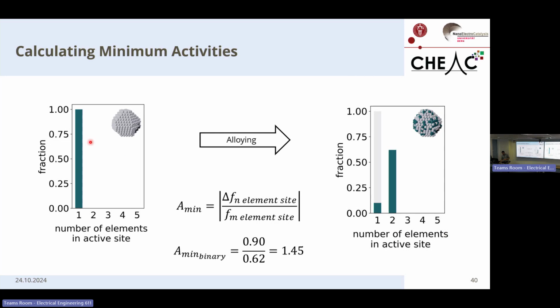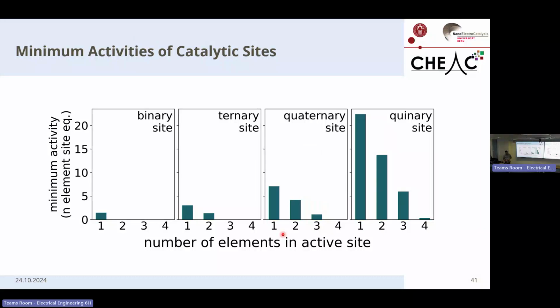If we start with a pure metal catalyst and we make a binary alloy, we lose 90% of the pure metallic surface to get 62% in return. So the only way this binary alloy is going to compete with its pure metallic counterpart is if these binary alloys have an activity of 1.4. We can continue this calculation pairwise, and now we see the struggles that high entropy alloys face.